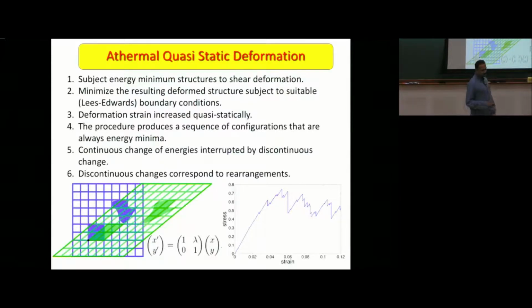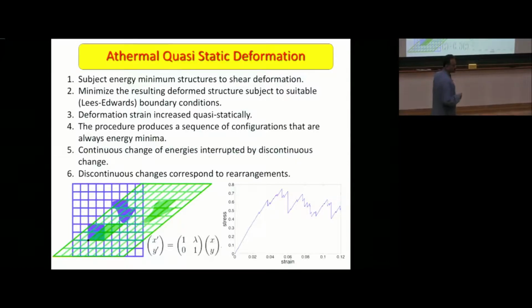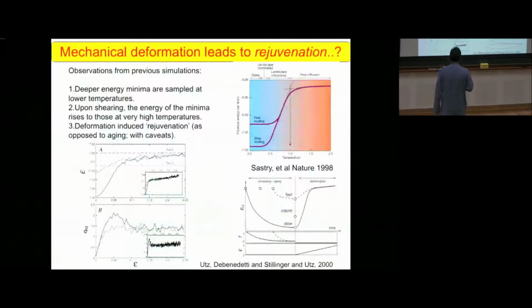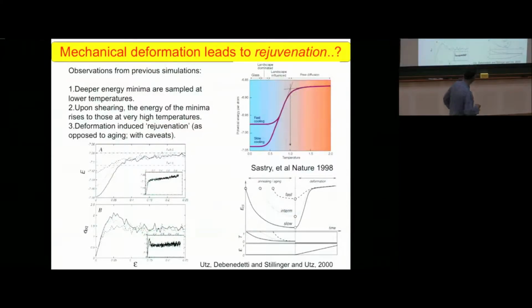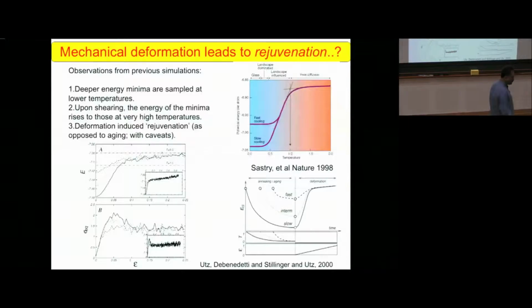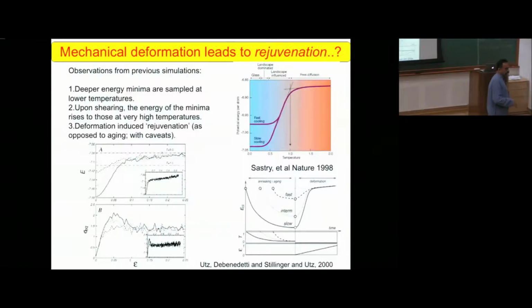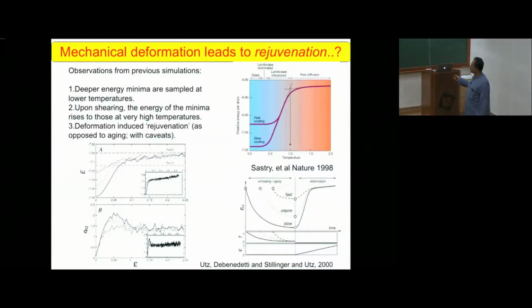I think I've said all of this. So if there's any question of what we're doing, this is a summary of the athermal quasi-static procedure. We deform, minimize the energy, we deform again, minimize the energy, and we keep going. If there's nothing happening, you'll see some elastic branch. If you have restructuring events happening, you see stress jumps and energy jumps, okay? So people have looked at this, and here is some old work. Now, if you just look at a liquid and map liquid configurations to local energy minima, you get a temperature-dependent average that looks like this.